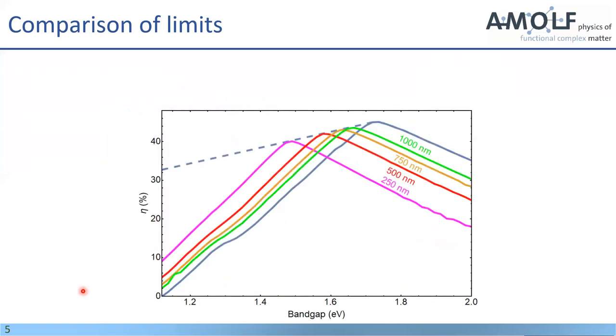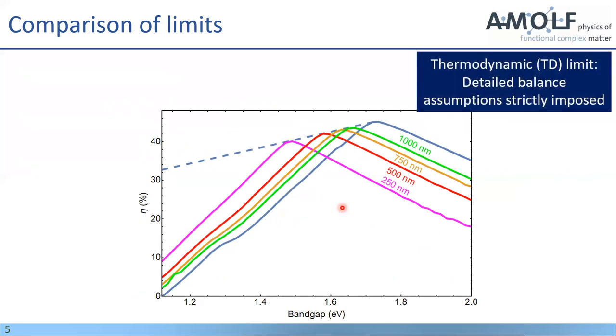And that's what you can see here. So first of all, we started by just strictly considering the assumptions in the detail balance, so perfect absorption in both layers. And that gives you this blue limit that peaks here around 1.7, 1.75. And this gives you the overall highest efficiency that you can get. And you see that for top cell, for perovskite top cell band gaps that are higher than that, you will also always be limited by this limit.